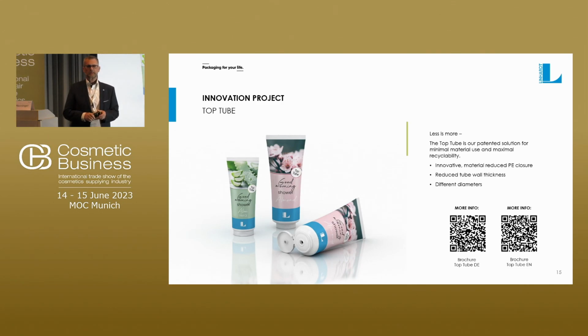was reduced in weight by approximately 15%, so if only using shoulder plus top compared to other low profile or shoulderless tubes, we can save up to 40% in material, and with regard to the overall tube, for a big 50 tube, for example, up to 20% of material compared to other comparable low-profile closure tubes. Compared to a conventional flip-top tube, we would save even way more.